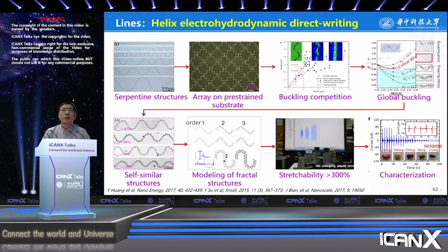Now I show how to fabricate serpentine structure and the self-similar structures. So it's a very long process. Firstly, you have to fabricate the serpentine structure and then put it on a stretchable, pre-strained substrate. When releasing the substrate, the serpentine structure will buckle, and you have to control the buckling direction. And another important question is how to make the global buckling, not the local buckling. Finally, we can get the self-similar structures.